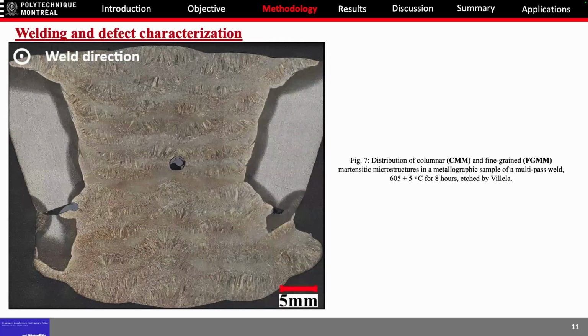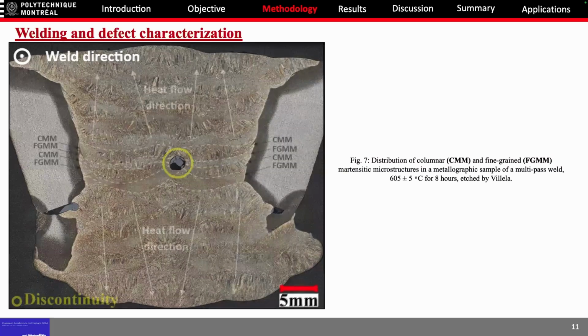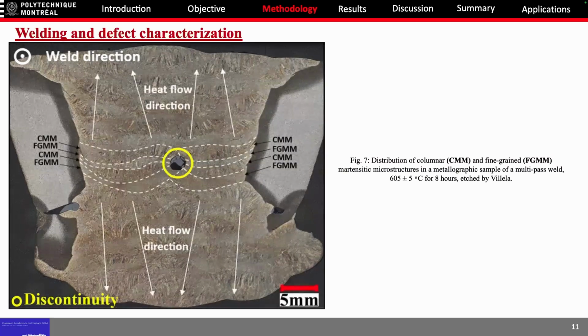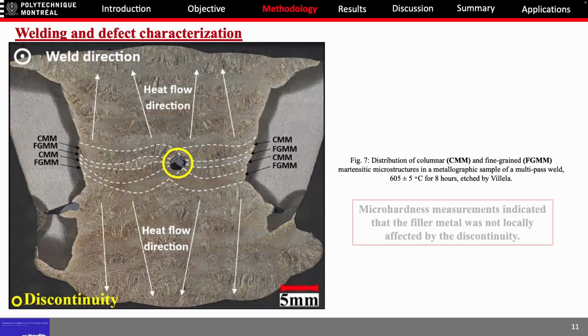This is the metallographic sample transverse surface, and as you can see in the middle, this is the discontinuity, which is surrounded by the yellow circle. It is surrounded by a distribution of columnar and fine-grained microstructure. Microhardness measurements indicated that the filler metal was not locally affected by the discontinuity.